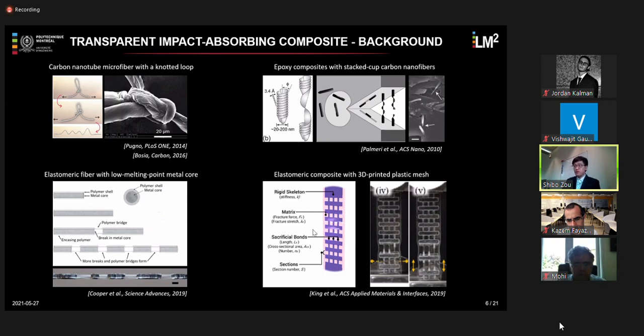And in the two examples below here, they use two systems, two networks in the material system. One is the weak component inside as a core or as a reinforcement. And the other one is the strong matrix material as a shell or just as a matrix material. And upon loading, the inner material, the weaker material, will experience sequential breakage, which is similar to the sequential breakage of sacrificial bonds. So in this way, they also achieved improvements of the toughness of the material under static loading conditions. So for two decades, the sacrificial bonds toughening mechanism in spider silk has been regarded as a perfect strategy for shock absorbers.